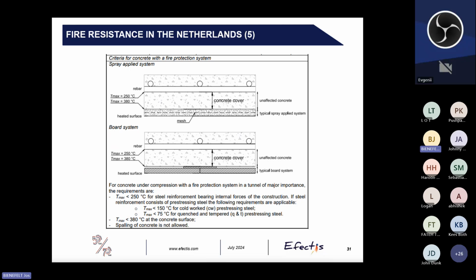This is again a picture from the procedure, which gives criteria for a fire protection system. Normally a maximum temperature is required of 380 degrees Celsius on the surface of the concrete and a maximum temperature of 250 degrees Celsius at the first structural reinforcement layer.